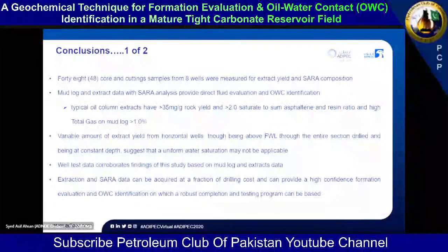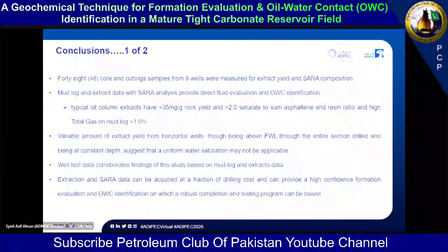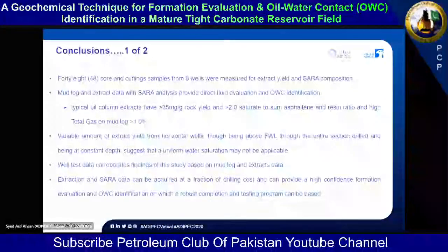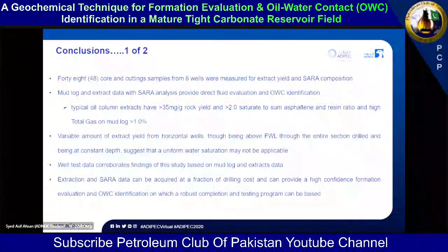Variable amounts of extract yield from horizontal wells, despite being above the free water level through the entire section drilled and being at constant depth in the horizontal section, suggest that a uniform water saturation may not be applicable. So when we are drilling a horizontal well, we assume that this horizontal well will have a uniform oil water saturation, which we have shown is not the case. Even if the trajectory of the well is almost at zero angle, there is a variation in oil saturation. And that can be measured directly using pyrolysis of the well cuttings, more or less in real time.